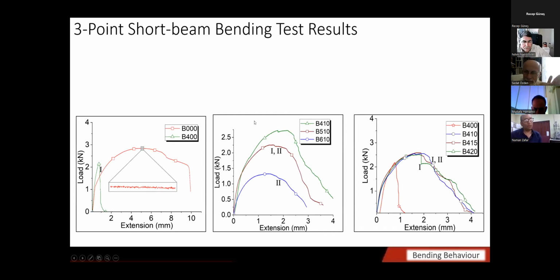These are the results of the wire reinforced bulks 3-point bending tests. Quite interestingly, the B000 specimen has behaved extremely ductile, and the B400 specimen has substantially low load and it fails very quickly. So the claim which we made while studying the tensile behavior of the wires, that geometrical discontinuities are a very important phenomenon, must be taken into account while doing the bending tests.